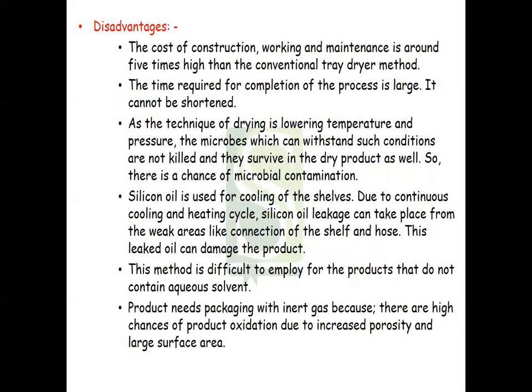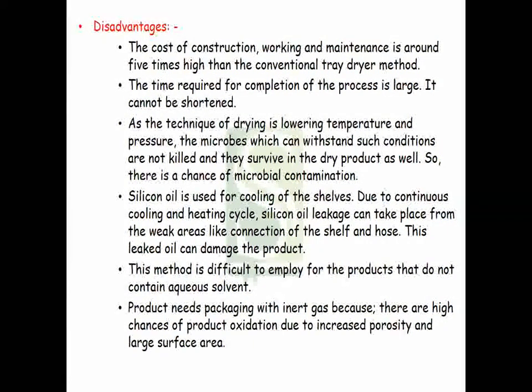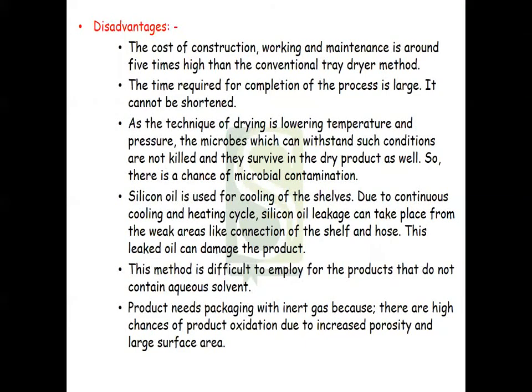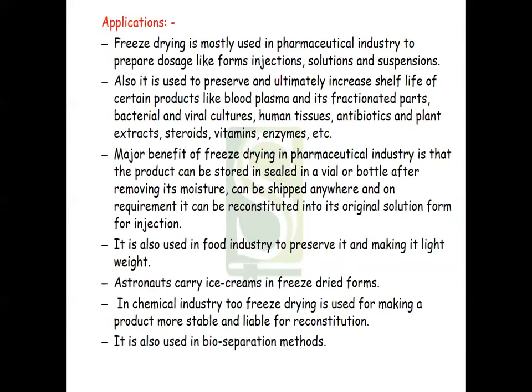Silicon oil is used for cooling of the shelves due to continuous cooling and heating cycle. Silicon oil leakage can take place from the weak areas like connection of the shelf and hose. This leaked oil can damage the product. This method is difficult to employ for the products that do not contain aqueous solvent. Product needs packaging with inert gas because there are high chances of product oxidation due to increased porosity and large surface area.